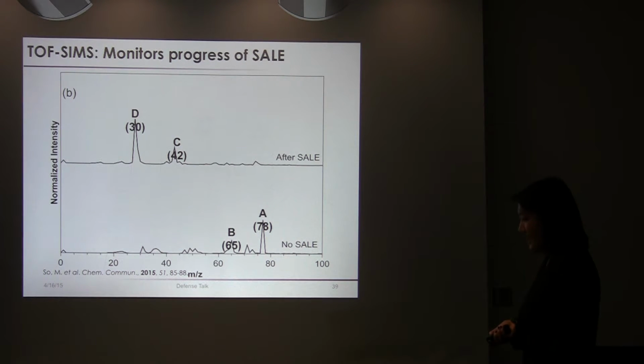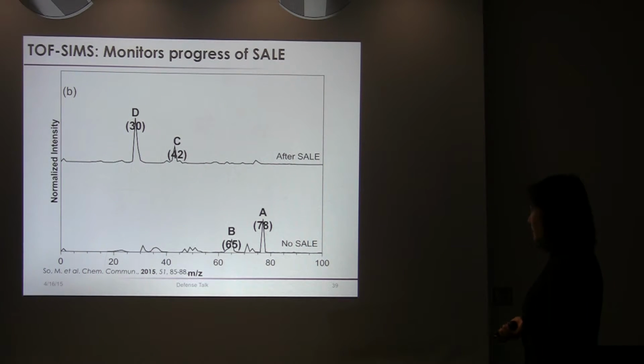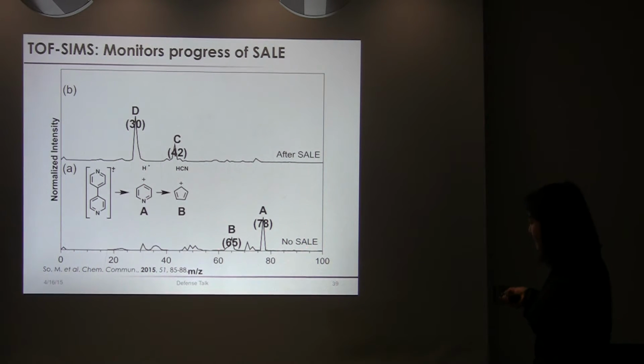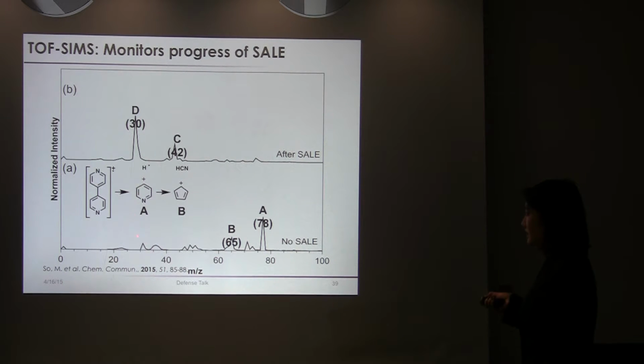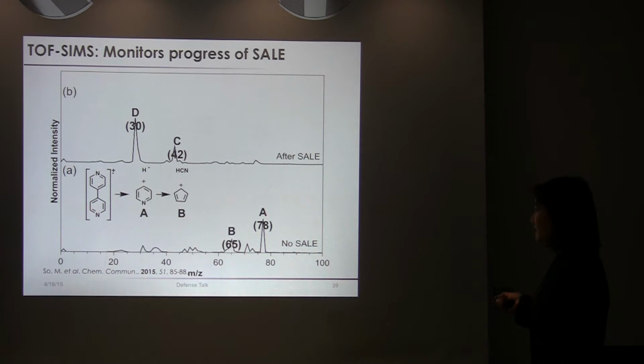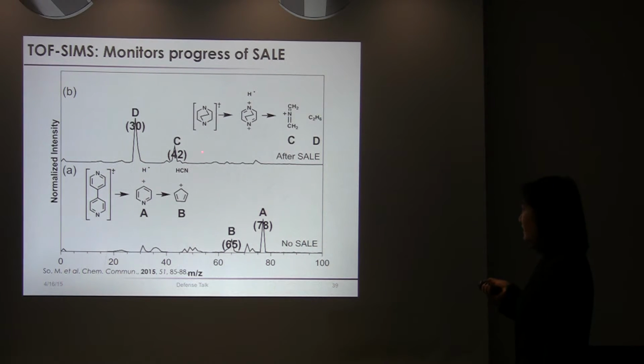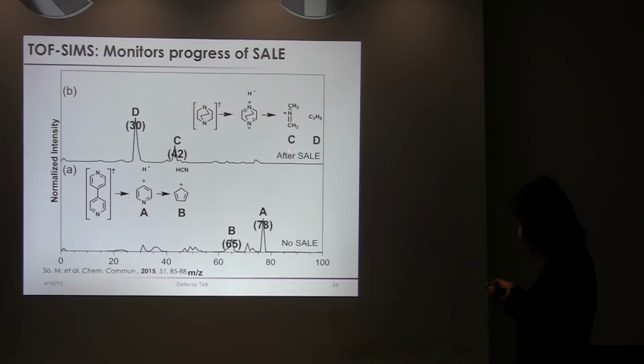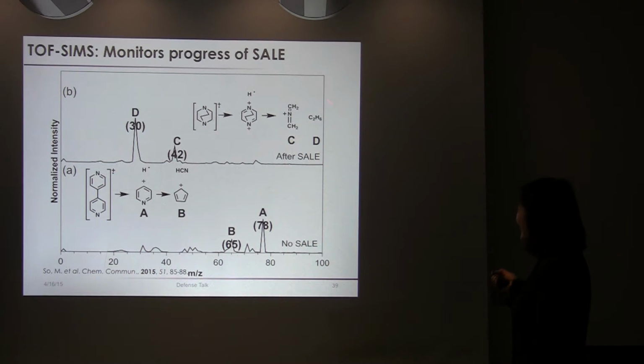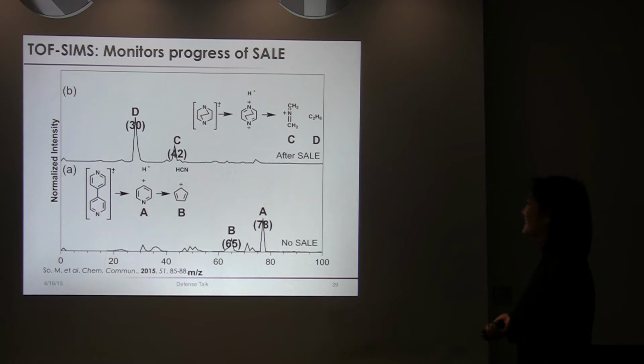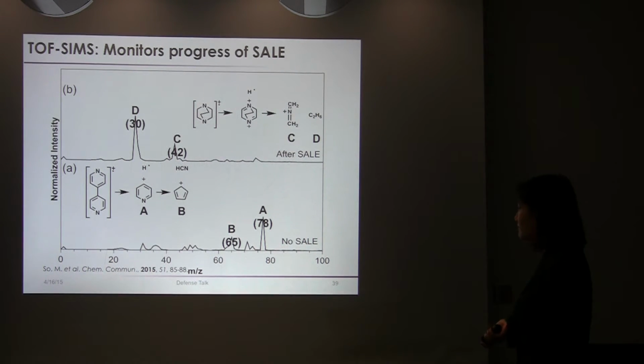Okay. So with TOF-SIMS, I collected spectra of an L2 MOF film. In the case where there is no SALE, I expected that this bipyridine linker would fragment into this pyridinium ion A, as well as this 1,3-cyclopentadienium species B. And indeed, without treatment of SALE, I had only seen these fragments A and B. But after 13 hours of SALE, I would only see fragments of the DABCO, which would fragment into this methaniminium and this ethane species D. And essentially that is what I see in the spectra after SALE.